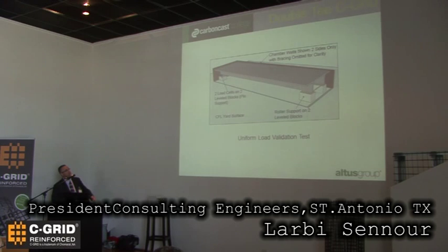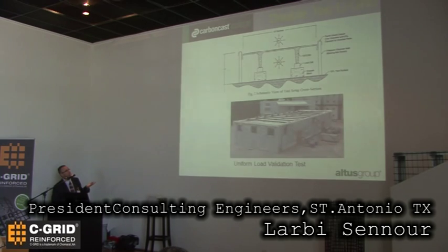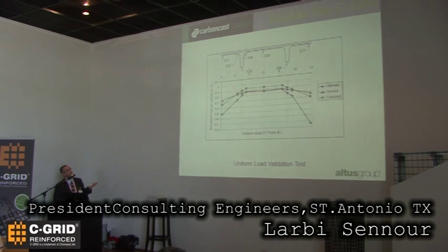We've done the load test. It was done in a chamber for a uniform load. This is what the chamber looks like. So basically, you put your double Ts and then you suck the air out, and that gives you the pressure. That's how you apply the load. And then we measure the deflections to verify the formulas we are using for designing that grid, and it correlates beautifully.